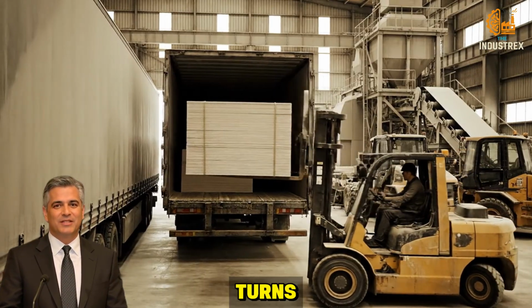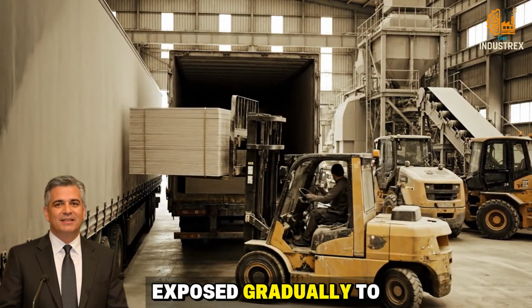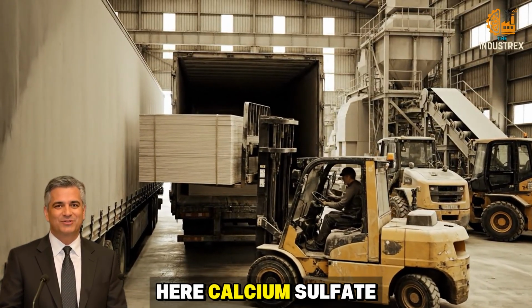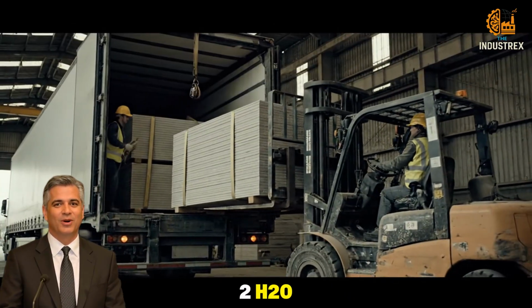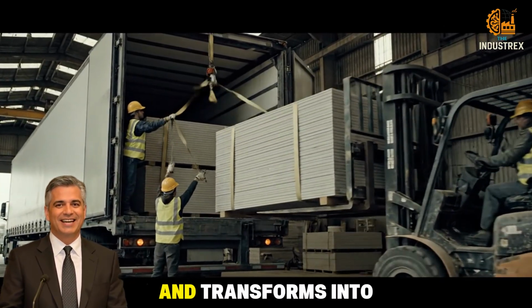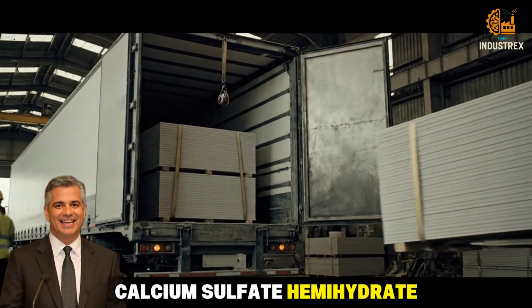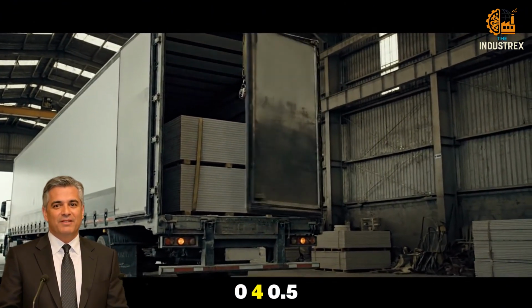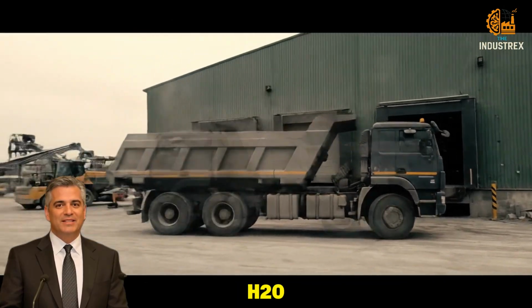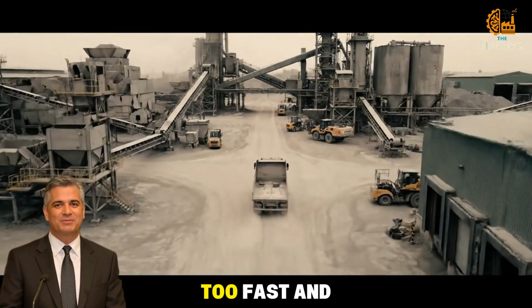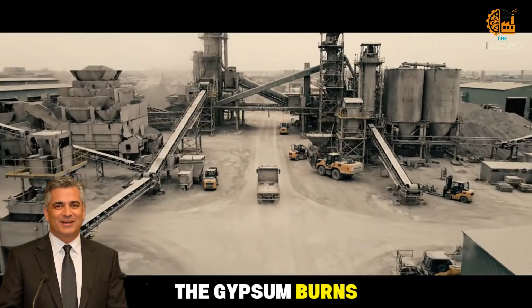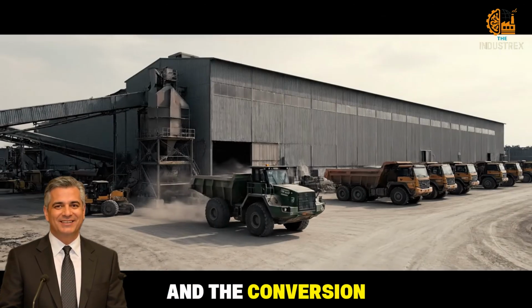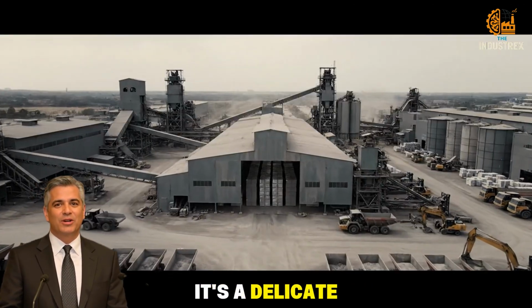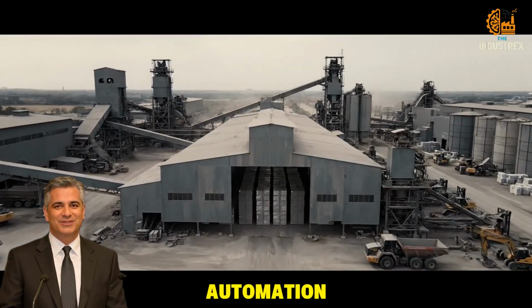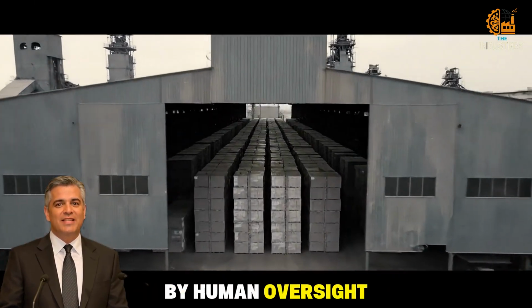As the kiln turns, the powder is exposed gradually to rising heat. Here, calcium sulfate dihydrate, CaSO4·2H2O, loses its water molecules and transforms into calcium sulfate hemihydrate, CaSO4·0.5H2O, also known as stucco. Too fast and the gypsum burns. Too slow and the conversion stays incomplete. It's a delicate balance, choreographed by automation and fine-tuned by human oversight.